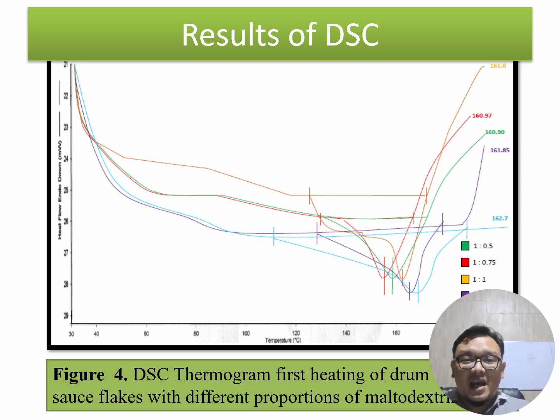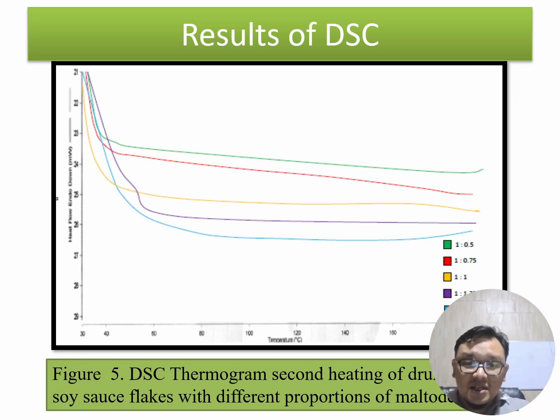For the DSC, in the glass transition temperatures, the reading became somewhat erratic. The explanation, which is supported by the thermogravimetric analysis, is that the volatility present in the soy sauce also affected the temperature reading. As you can see, the first and second heating indicate the temperatures of the materials to determine the crystallization and melting temperature. Okay, so this is the result of the thermogravimetric differential thermal analysis. As I mentioned earlier, there are some limitations on the machine because of the volatility. So after the DSC, it was suggested to perform DTA to determine why the results of the DSC were affected.